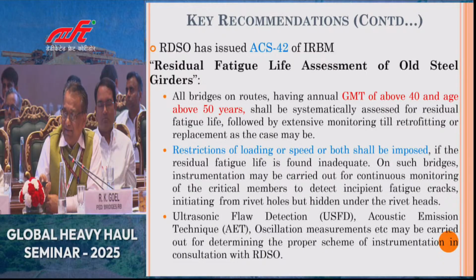And the restrictions of loading or speed or both shall be imposed as per these correction slips. This has been made part of the manual so that the people do not get any resistance from the operating department. And then ultrasonic flaw detection, acoustic emission technique, and other oscillation measurements, etc., may be carried out for determining the proper scheme of instrumentation in consultation with RDSO.